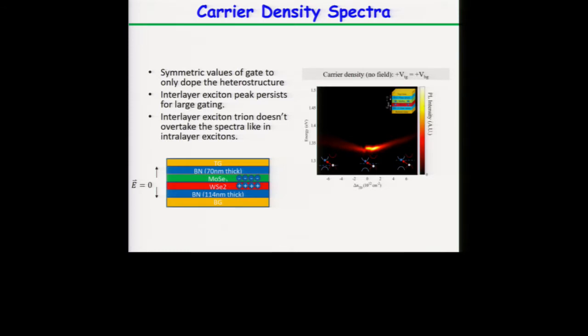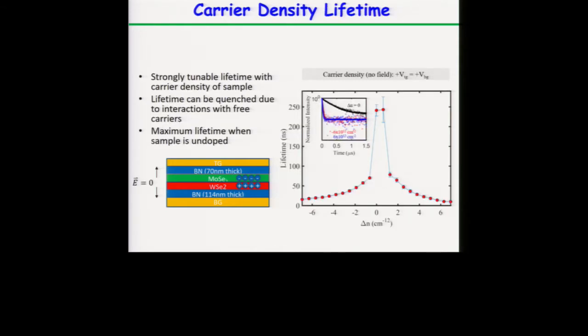But there is not much of a shift in the peak position, but the lifetime gets dramatically reduced. The lifetime goes from 250 nanoseconds at zero gate to close to 10 nanoseconds once we dope the samples together. There is no electric field, so we make sure that we are not applying an electric field across the sample. It's mainly just doping the layers.